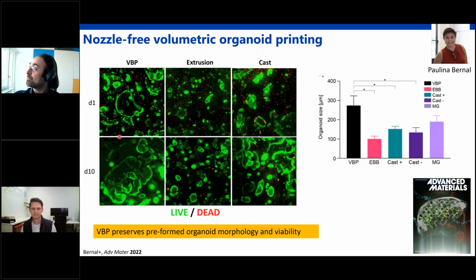At the beginning, when we were working with larger volume, we were even trying to stir a bit by placing a mini stirring bar inside the vials to keep the organoids afloat. But in the end, we realized that the gelation is so quick that we don't need to do it. So we don't have any problem of a different distribution of cells across the height of the construct.